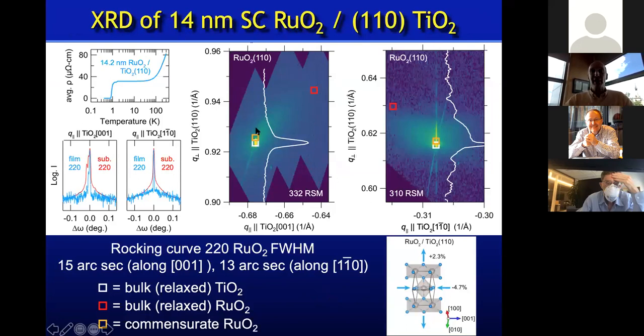This is a reciprocal space map made on one of these thin superconducting films. This one's just 14 nanometers thick. The various boxes here are telling you where you would expect the peak of the film and the substrate to be, if it's commensurate or not commensurate. The substrate should be where this white box is. So that's where the bulk reflection of TiO2 is. That's the substrate. The film, if it's fully commensurate, should be very, very close to it. If it's fully relaxed, the film peak should be way over here. Okay. Now, when we look at it, it's hard to see, maybe it's relaxed a little bit, but it's certainly not way over there.